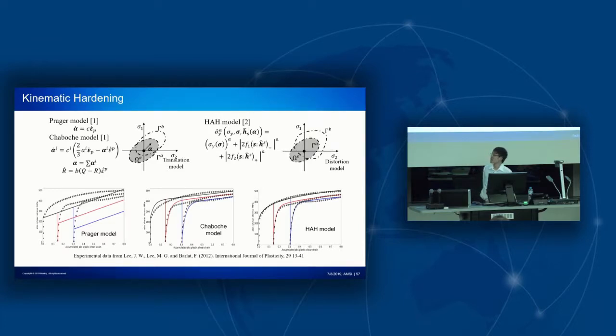The result shows here that both concepts can model the material kinematic hardening well. One is by translating the yield surface by introducing some back stress tensor. Another one is by properly distorting the yield surface by using something called the microstructure deviator tensor. But again, a more accurate kinematic hardening model means more computational cost.